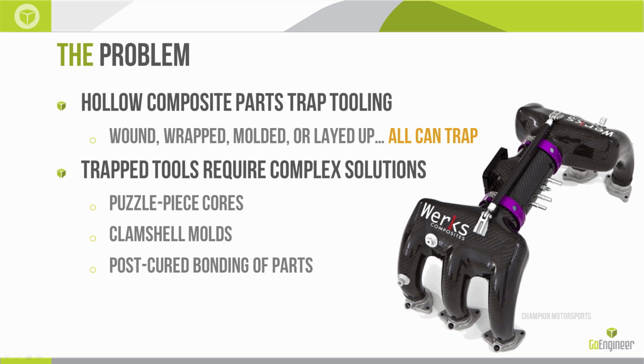Hollow parts are created by either winding them or wrapping them, molding, or laying up a carbon fiber sheet or strip or mat, wrapping it around a shape and curing that. You create a hollow part by then, after the curing, removing that shape. And in a lot of cases, that shape would become trapped after the carbon fiber is cured or hardened. In the case of something like a tube or a cylinder, that wouldn't really be the case. But more complex shapes can become trapped, and that's where the problem lies.